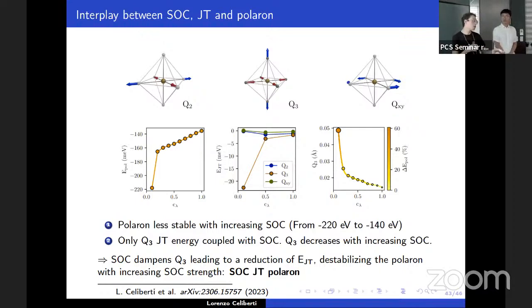So with the pristine material, you have non-zero magnetic moments with this canted phase. Then if you go on the other side of the phase diagram, you don't have magnetic moments, they're at 0, and you have these octopoles. But the magnetic transition in between is not really clear, and the state of the polaron is not yet clear. All this calculation was performed with a non-zero magnetic moment, keeping the magnetic structure of the pristine material.